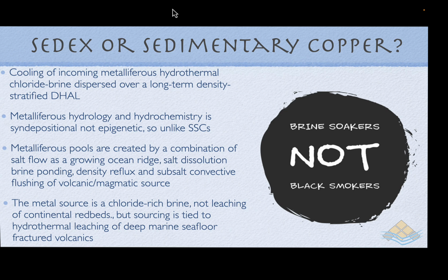The metalliferous pools, however, are created by a combination of salt flow at what is a growing salt ridge and salt dissolution. So salt dissolution is an important component here, like it was in the various stratabound sedimentary copper deposits. And also subsalt convective flushing is important in this system as it was in the sedimentary copper deposit. The metal source is not leached continental red beds, but it's tied to the hydrothermal leaching of these deep marine fractured volcanics. They're not sedimentary copper deposits in the terms of red bed source sedimentary copper deposits, but aspects of the hydrological focusing tied to the evaporites are common to both the sedimentary copper and the SedEx deposits, as we shall see in the other examples from this course, and also when we look at SedEx deposits and the importance of evaporites in creating giant SedEx accumulations in the lead-zinc world.